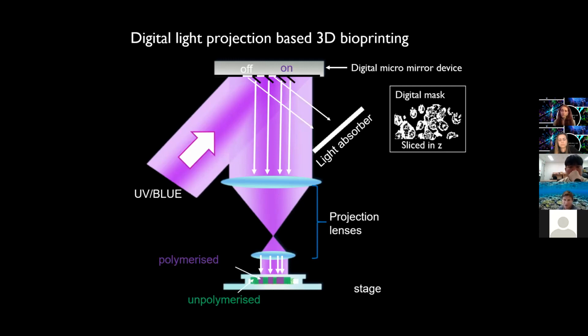And then you create patterns, right? And then you load the next mask and the motor. So we have a motor in here. The motor moves, and by that you have some kind of continuous printing. So very smooth structures, and I would say less artifacts between layers. And also quite good spatial resolution, down to less than 10 micrometer. So that's the principle.